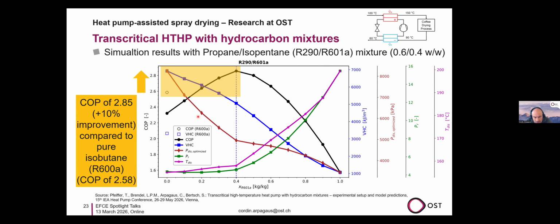And this is almost my second last graph. But it shows some theoretical simulation results of this hydrocarbon mixture of propane and isopentane. Here is the isopentane mass ratio. So here we have 0. So this means here on the left we have only propane R290, and here on the right it's full isopentane. And then you can see here the black curve, that's the COP. And you see a maximum, and this means at 40% isopentane and 60% propane, the efficiency is highest for these particular applications here on the right.